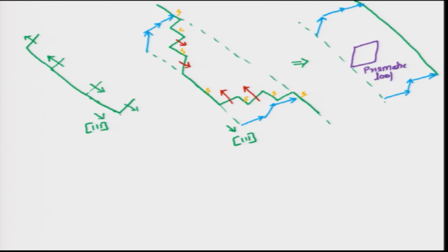So, there have been observations of structures like this, where in BCC, particularly tungsten, you would see long screw dislocations, and by the side of them you would see prismatic loops. So, this is what we have covered, a lot about the dislocations, particularly about the screw dislocation, which makes them very different from FCC. So, we will end our study of dislocations in BCC, and next time when we meet we will start with another system, which is HCP.